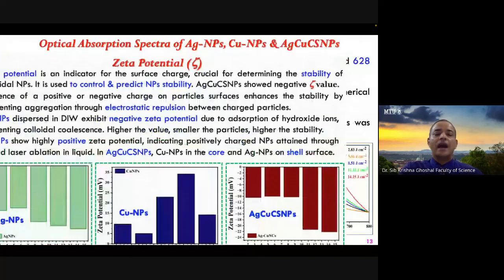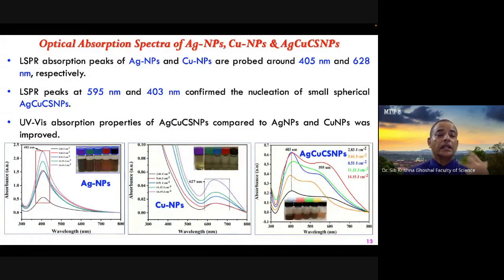And these core-shell nanoparticles are extremely useful for antibacterial applications. Now, how do I know these nanoparticles have very strong optical properties? Say they have strong optical absorption properties. Here you can see the absorption spectra of this nanoparticle, and with the naked eye, we can see their color. As we change the laser fluence, the size of the nanoparticles changes. So we can see the localized surface plasmon resonance peak tuned from 595 nanometer to 403 nanometer. So this is from the green to the purple to the bluish end. So based on the size, we can create different types of color, different types of surface plasmon resonance in this particular nanostructure.